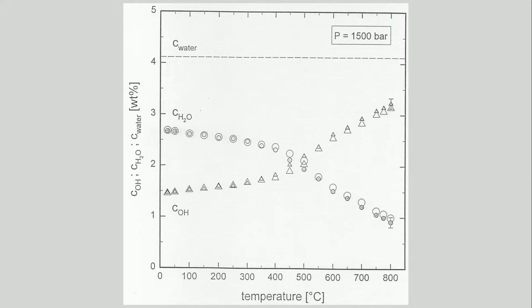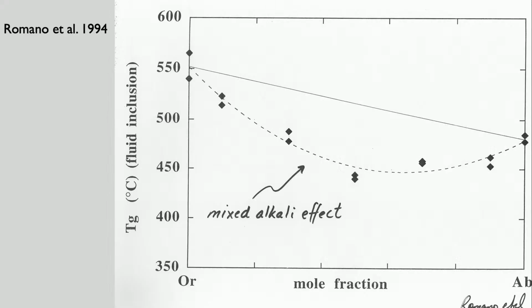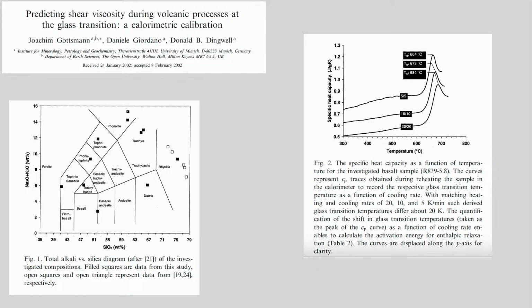Okay, I'm going to jump ahead a little more past some of the details that I want to avoid. So we have the opportunity to compare viscosity versus calorimetric glass transition temperatures. It's a way that we can use to obtain the viscosity of heterogeneous samples, and a way that we can use to obtain detailed information on the chemical dependence of viscosity. And we can do this because the relaxation which causes the CP curve to jump, as you've seen, is the same process which causes the rock to physically relax stresses, and therefore is recorded in the viscosity of the material.